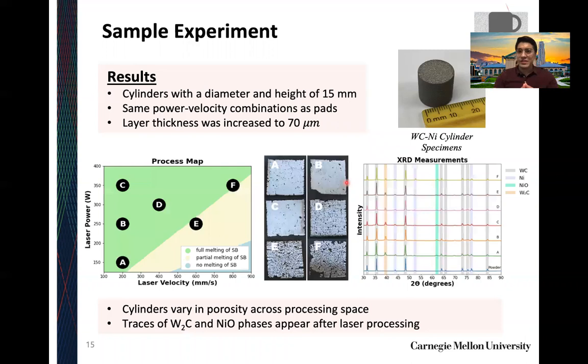So by inducing this thermal warping, our recoater blade would come across, and if the part was warped high enough, could come in contact and impact and thus shear off our cylinders. So we did some problem solving and realized we can increase the layer thickness just a little and still build up parts, but make sure we don't come face to face with this obstacle again. And here you see our results.